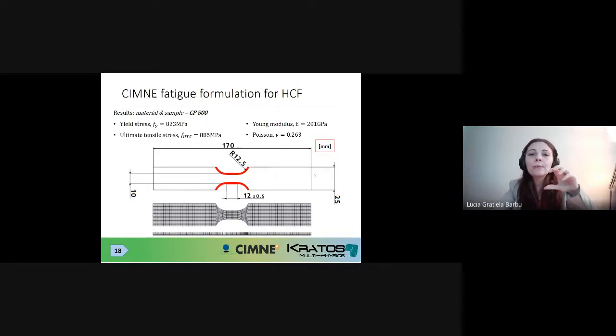In order to do this, as I say, we've been working with Eurecat, and we've done a study on the complex phase 800 steel. This is the shape of the specimen which they tested, and this is the finite element model that we've used in our numerical simulation.